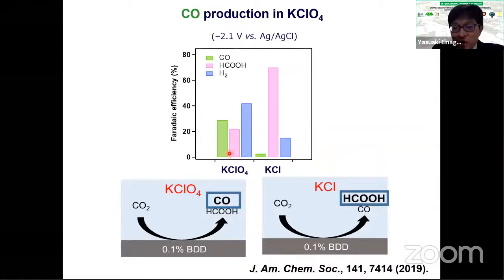And this data is a little bit old. Recently, we optimized the condition, and now we achieve 70% Faraday efficiency for carbon monoxide. This was one year ago: the first data showed 30% carbon monoxide, but now 70% is possible. Anyway, when we control the anion, as you can see, we can control the product. For example, if we want to get carbon monoxide, we should use perchlorate, and when we want to get formic acid, we should use KCl solution.